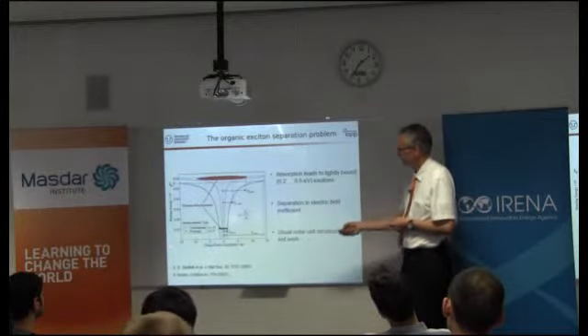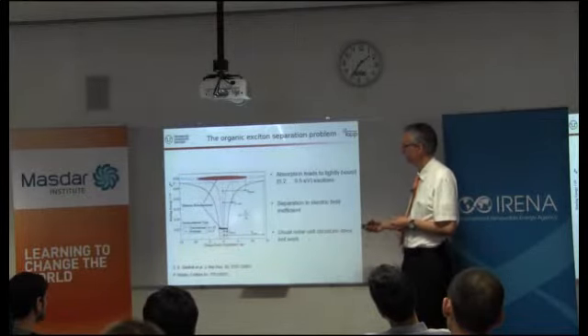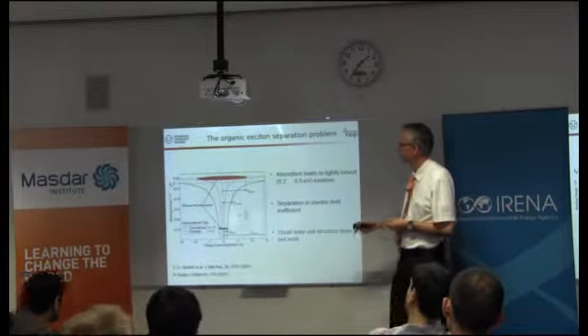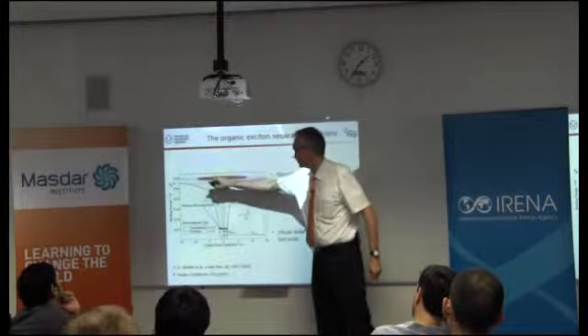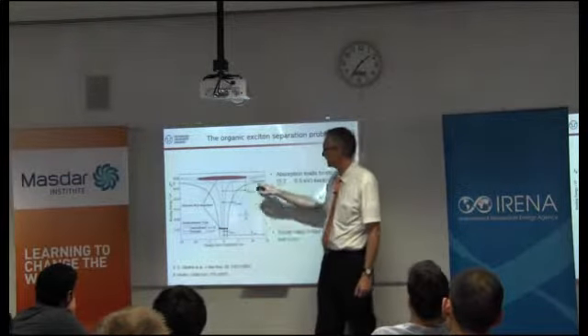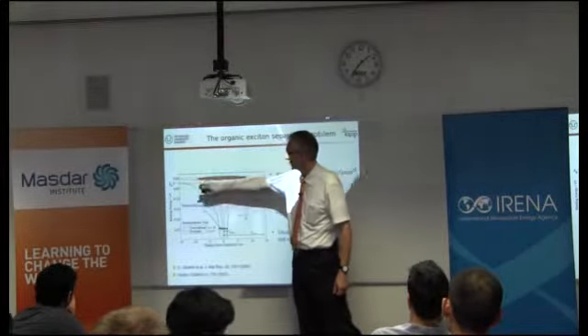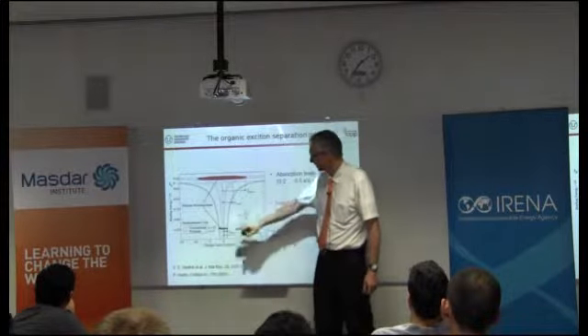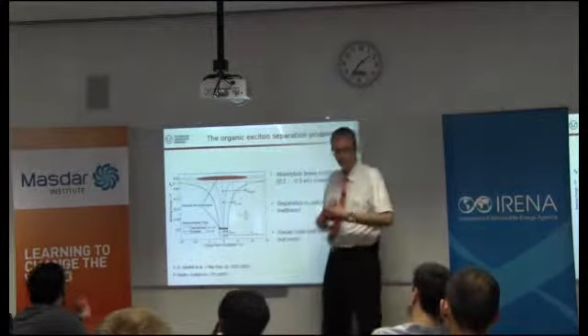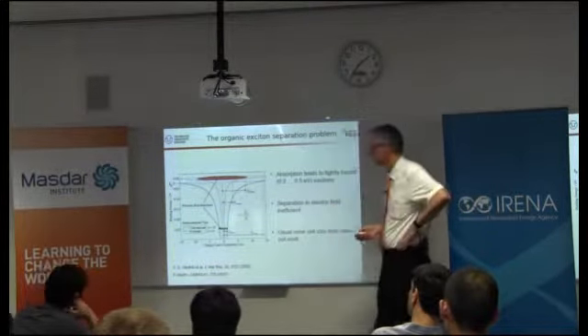This is the spatial coordinate, and this is energy. And an exciton in silicon or gallium arsenide is very large, about 20 nanometers large. And the binding energy, this is kT, room temperature. The binding energy is very small, whereas the organic exciton is very tightly bound and very small. So it's hard to separate.